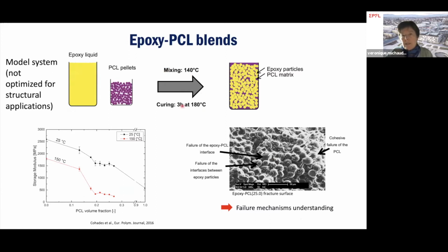So we started exploring these blends and worked on model systems, with the epoxy and PCL, mixing, curing 3 hours at 180 degrees. And then we got phase separation. In our case, we found that about 25% of PCL was the good one that we needed. And then we see, of course, that the storage modulus at 25 degrees and 150 degrees, which is the healing temperature that we will use, is decaying with the presence of PCL in the matrix. However, it remains in a range above 1 gigapascal, which is acceptable.